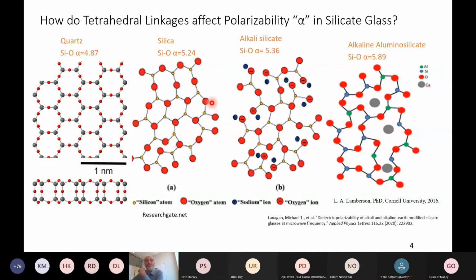And then we start adding impurities, like I showed the window glass. And in this case, we can see where these structures break up even more for adding sodium, or maybe in this case calcium. And then the one thing that's important is we've fundamentally looked at what's called the polarizability, which is related to the relative permittivity or dielectric constant. And here we're going from a number 4.87 all the way up to 5.89. Not much of a change. And in fact, the permittivity values aren't that different. Here you're at about 4.5 for quartz, and here you're about 6. So maybe 20–30% change in the permittivity because of this extra motion within the material.